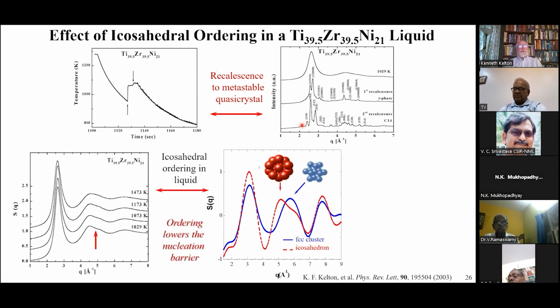If you looked at the liquid as a function of decreasing temperature, before we had recalescence, here's what it looks like. This is the structure factor as a function of inverse momentum transfer. The thing to notice, of course, is that it gets sharper. You can't really see that because I've offset the curves. But the reason I offset the curves was so that you can see this little shoulder that's developing on the high Q side of the second peak. By taking the Fourier transform of this, we can get to the pair correlation function. By integrating under the first peak of the pair correlation function, we know that the coordination number is 12.